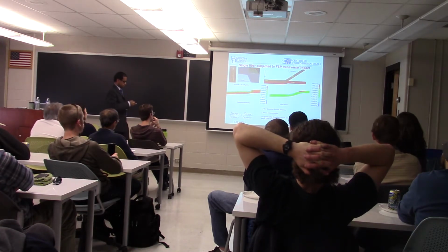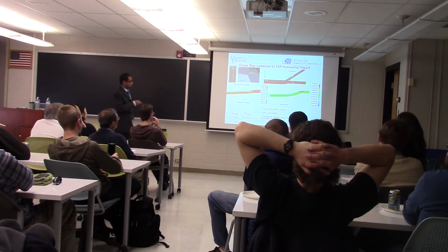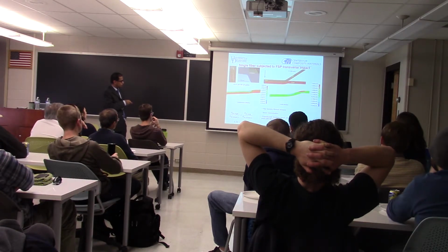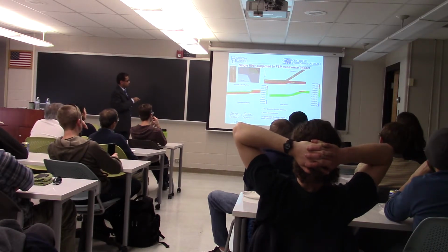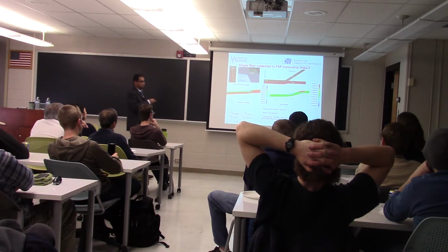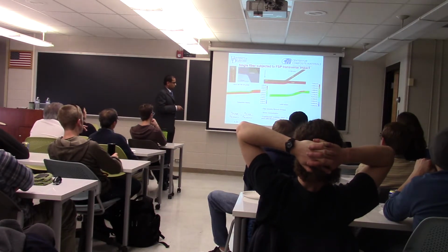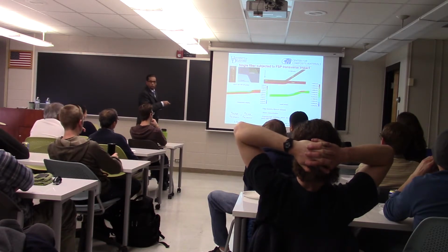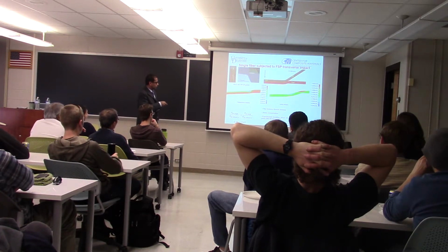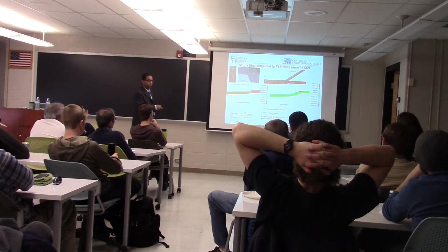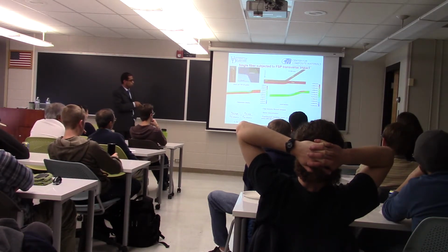Now this is an FSP projectile, that is, a fragment simulating projectile. It has a flat face and a sharp corner with a radius of about 20 micron for this case. So all the action is happening within this corner radius, where there is a significant local multi-axial stress concentration. We'll talk more about this a little later.